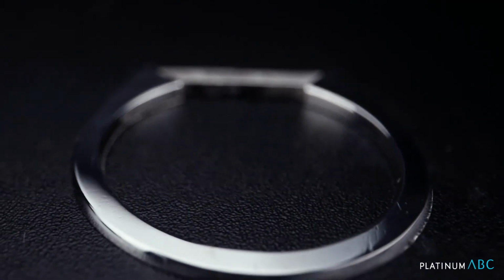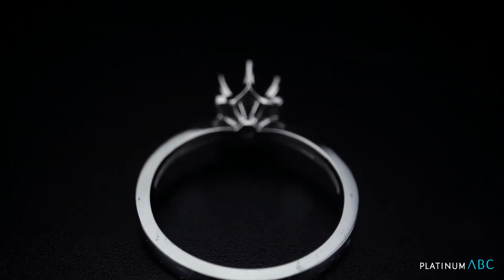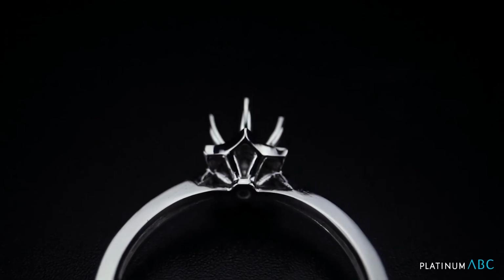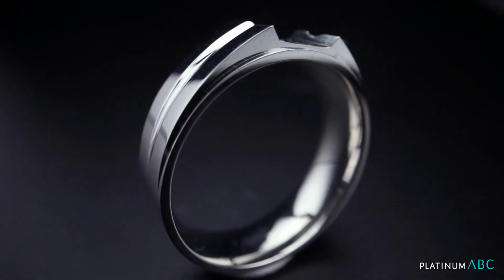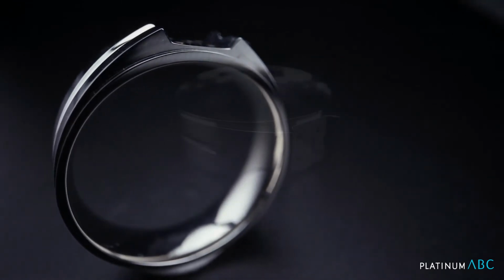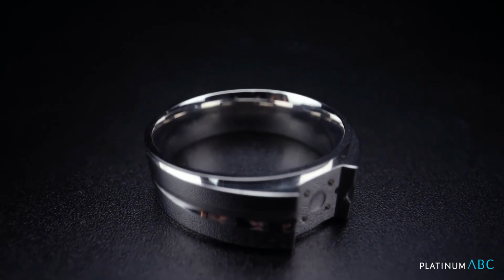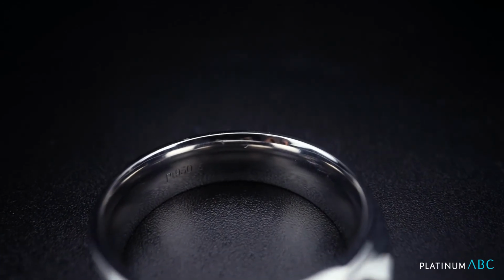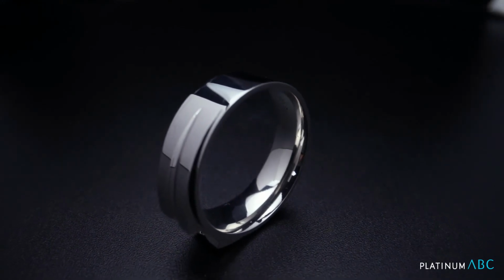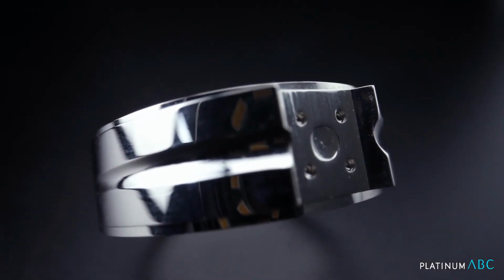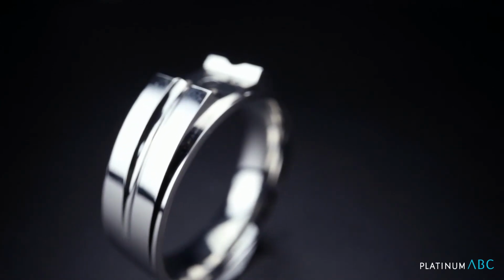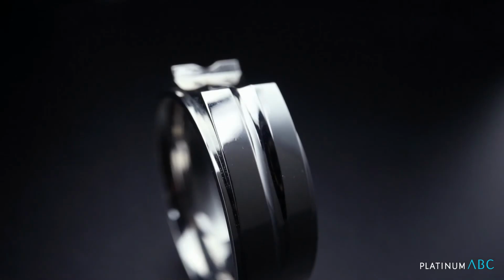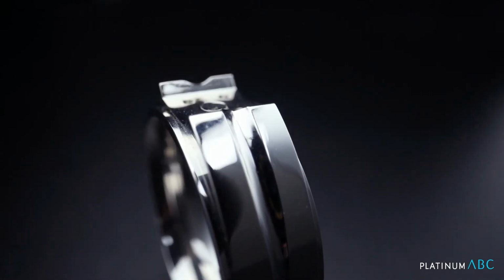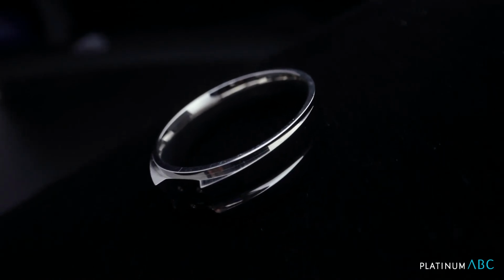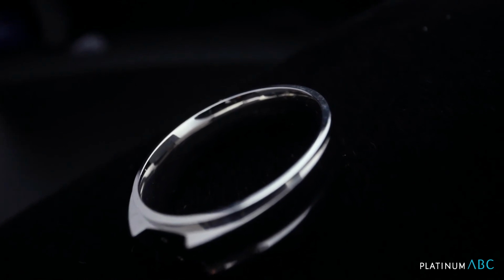And our operator came back and cast the 7th, the 8th, the 9th, and the 10th round of the recast himself. To our surprise, the porosity stayed the same across the subsequent 4 rounds of repeated casting. Porosity did not intensify, but it also did not improve. It stayed just as bad as the 6th round all across. This is a great insight because if nothing went wrong, there is nothing to learn from. In this case, porosity is clearly the result of inconsistency in the operation or handling of the casting process, not a problem originating from the metal itself.